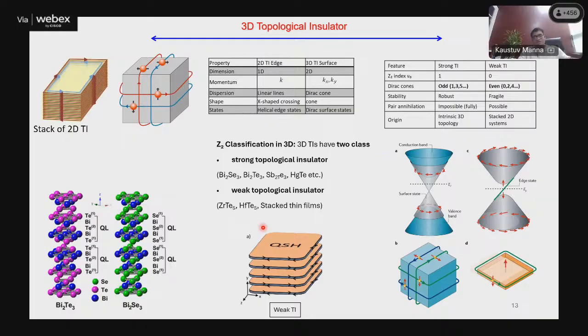Now from the 2D topological insulator, we are going to the 3D topological insulator. So what is the 3D topological insulator? You can imagine a situation where you have a metallic empty box. Empty box means inside is already air, which is gapped, already a trivial insulator, whereas the surface is a metal, the surface state. So this is the picture of a 3D topological insulator. You can construct the same by taking 2D topological insulators and stacking them on each other, so that you can make it 3D, like a stacking of 2D topological insulators.